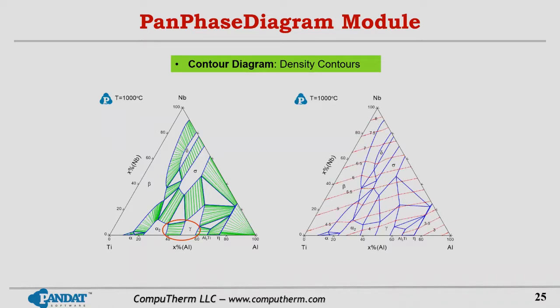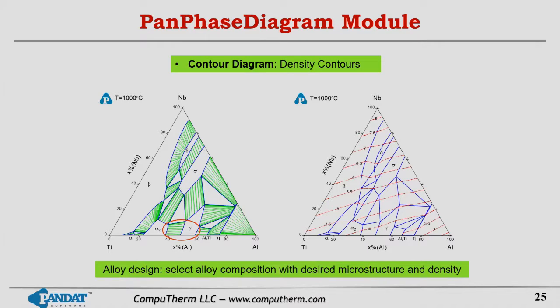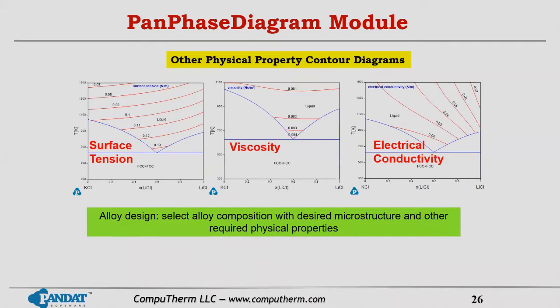However, if we put density contour lines on this phase diagram, we can immediately tell how much niobium we can add while maintaining the density of this titanium aluminide at a certain stage. This is also very useful information for alloy design. We can plot all kinds of contours of physical properties on the phase diagram, and this information helps users design alloys that meet both phase stability and property requirements, which is the major concern.